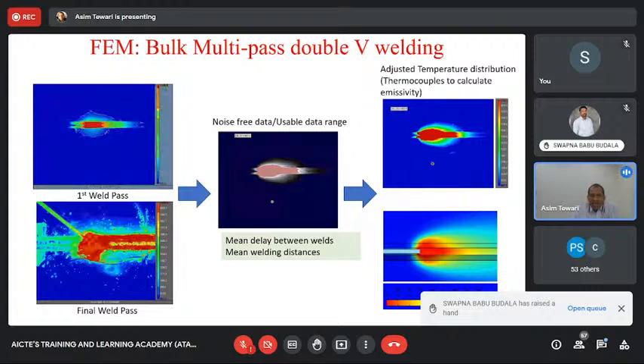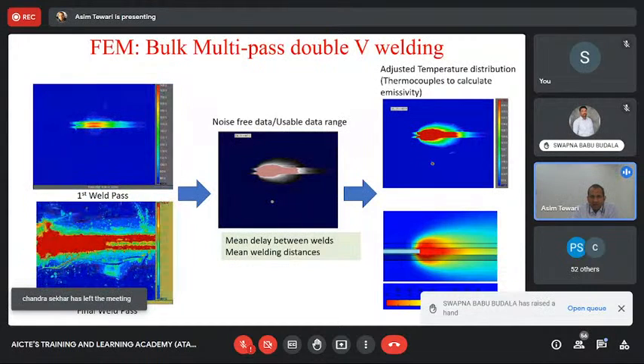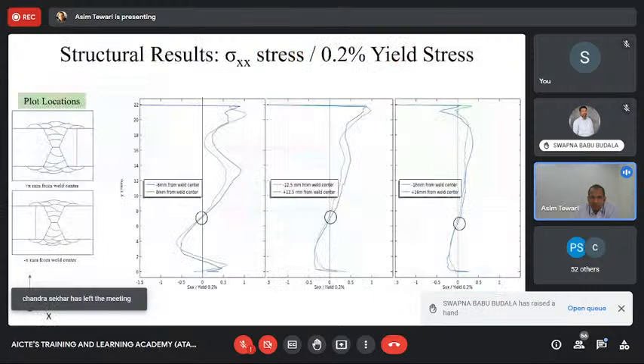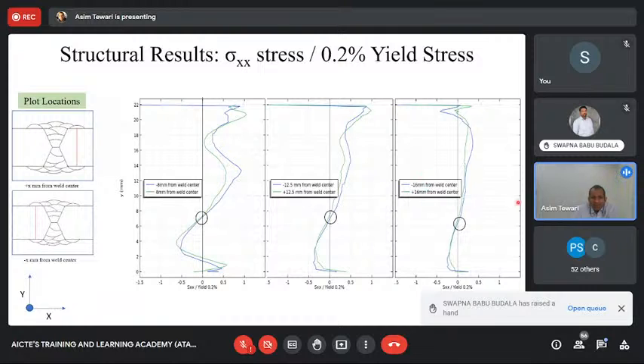So now this is the actual experimental thermal values which we calculated. And then we looked at how the residual stress would be varying. Now this is where we have added about 20 odd layers going from one to the other. And these are the layers which are being added one after the other. Build strategies could be different. You could add 1, 2, 3, 4 all over here and then add on the other side, or you could add few here, then there, and vice versa.